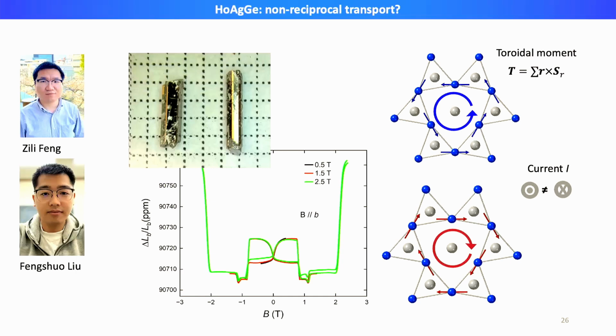we follow through across this hexagonal loop, you can see that the spins are sort of winding around the loop, and we can define a toroidal moment for this spin configuration, which is sort of the momentum of the magnetic bonds. So for this particular magnetic state, there is its time reversal pair, as shown here, where you can see that these spins would wind the other way if you go around the loop, and this would have an opposite toroidal moment